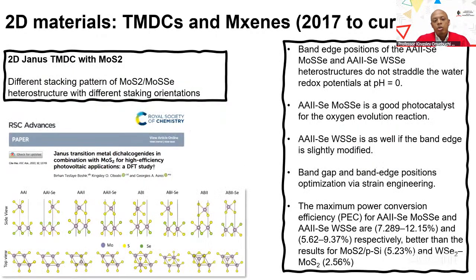So now, going back to what we've done, we've looked at different MoS2 configurations. I use the word configuration in the sense that you can stack one material on top of another material, and based on the different stacking, I can calculate whether this material is feasible, whether it will form, and what is the optimal configuration for it to form. The reason why we do this stacking is because we can reduce the recombination rate of this system. And that's the major reason.